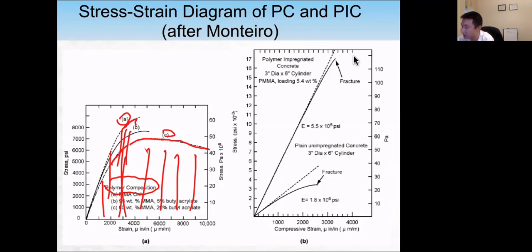The figure on the right shows plain concrete versus polymer impregnated concrete. We can see polymer impregnated concrete has much higher strength, and also the E value, which can be seen from the slope of the stress and strain curve, is much higher. So higher E value and also higher strength, but it is more brittle. There is not too much deviation from the straight line for polymer impregnated concrete, but for traditional concrete, the E value changes over the different strain, and it feels less brittle compared to PIC.